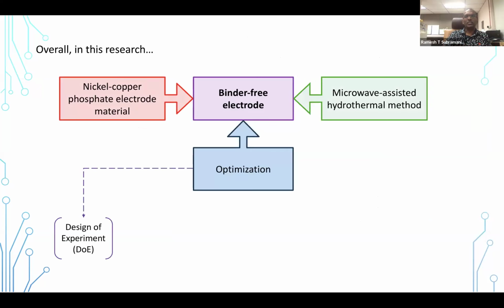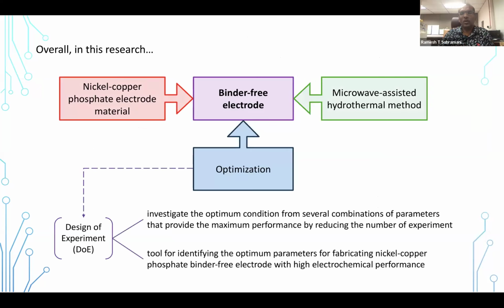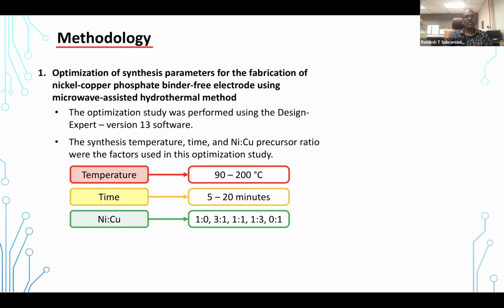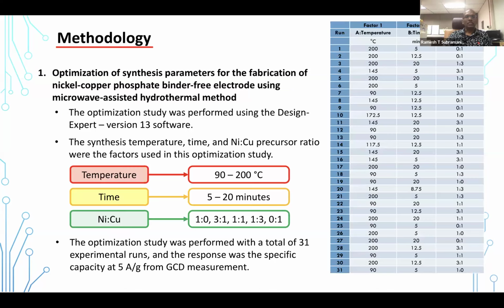Next, once we have this microwave assisted hydrothermal method, we use design of experiment to optimize the conditions needed for the experiments. For example, the temperature range can be from 90 to 200, the time from 5 to 20 minutes, and for the nickel copper ratio we have a few ratios. These ranges and ratios are based on the literature.